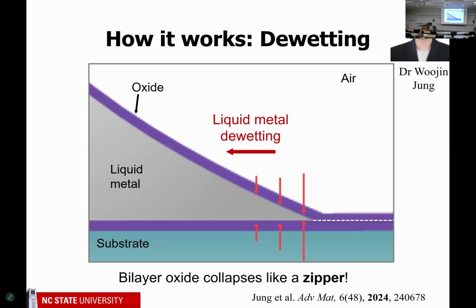I'm telling you kind of the high-level version of this, but Woojin gets a lot of credit because he sort of figured this out. The short version, without going into a lot of detail, is that the liquid metal inside of its own oxide actually has a very low surface tension. It really likes to be in contact with the interior of its own oxide until the contact angle that's formed right here gets low enough. And when it gets low enough, below about 20 degrees, it will spontaneously collapse. So it wants to be at around 20 degrees.